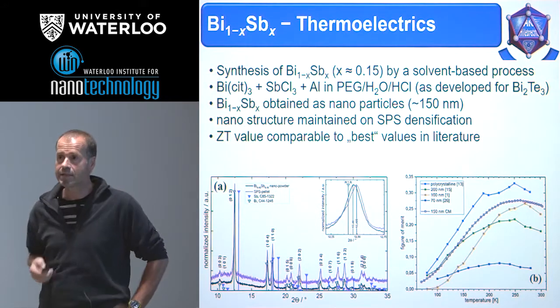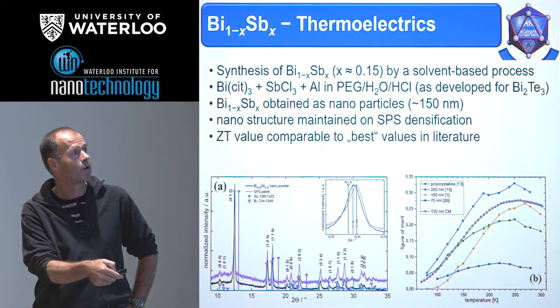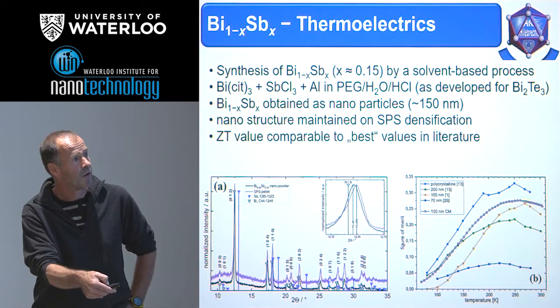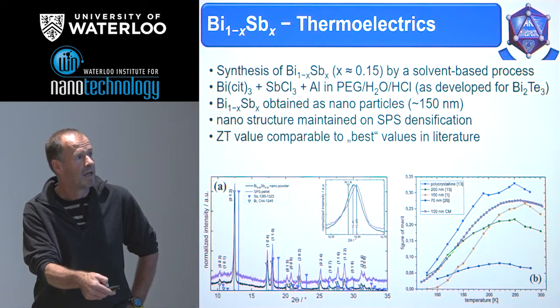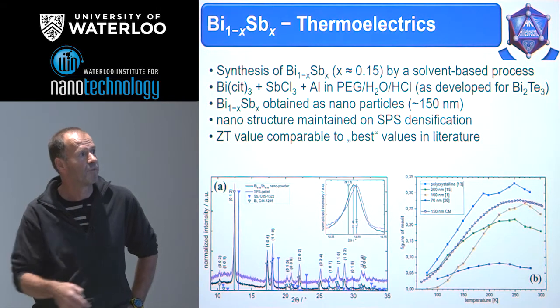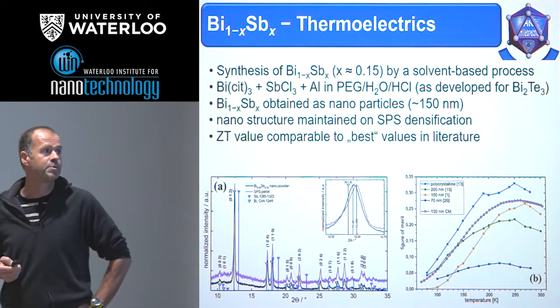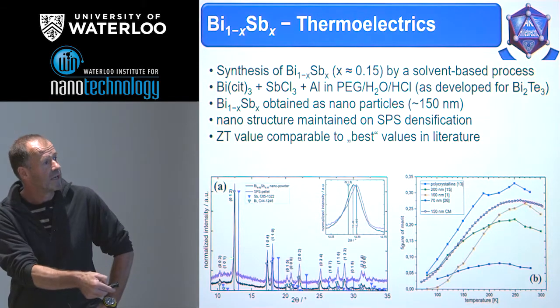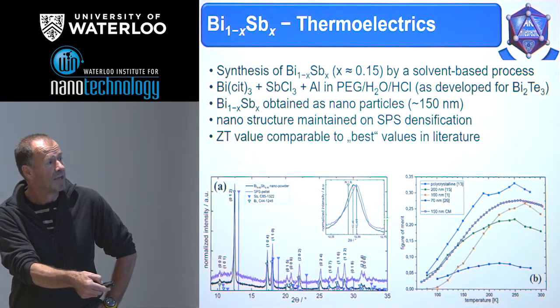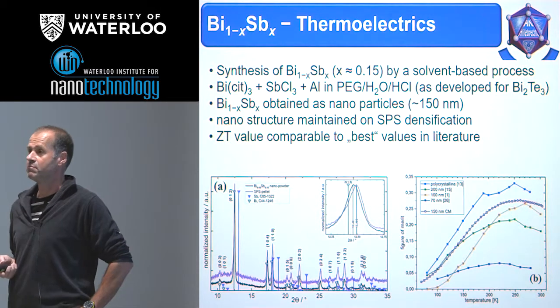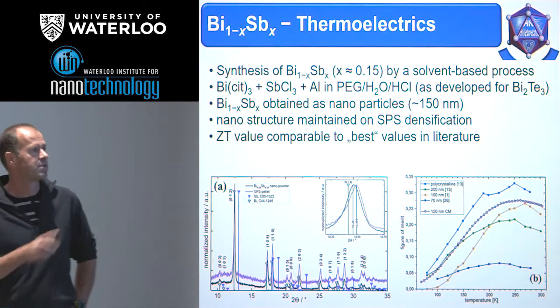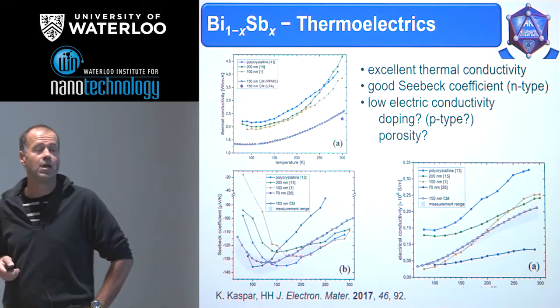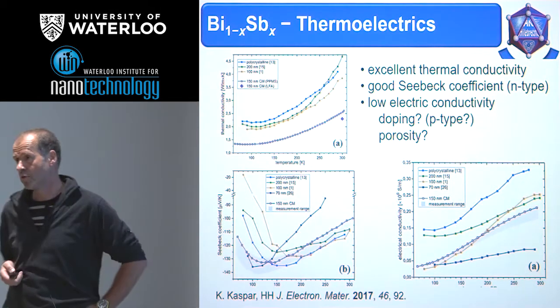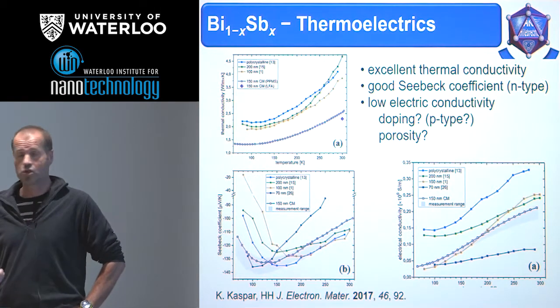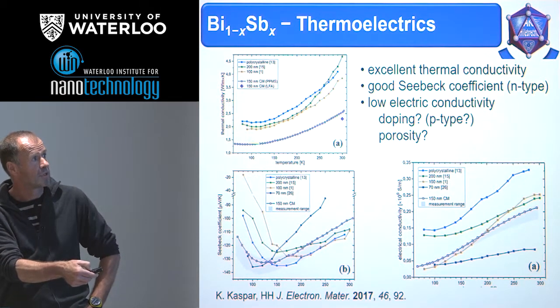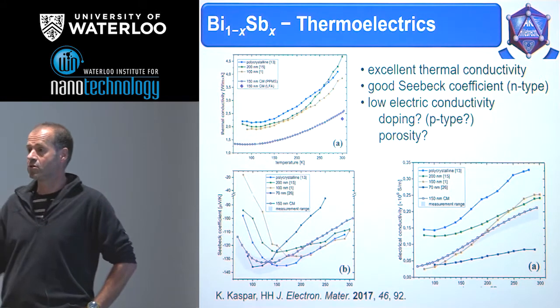And the ZT values that we obtained are comparable to the best ones. Our curve is the lilac one, and we see it's comparable to the best values which were published by other groups, and we could show that our process really results in quite uniform and homogeneous material, which is not so easy, but we were successful in that way. We have measured all the properties which are important for thermoelectrics, and we could show that we have an excellent thermal conductivity, which is a result of the nanostructured system.